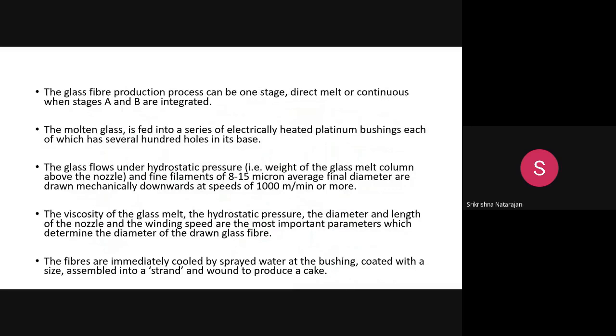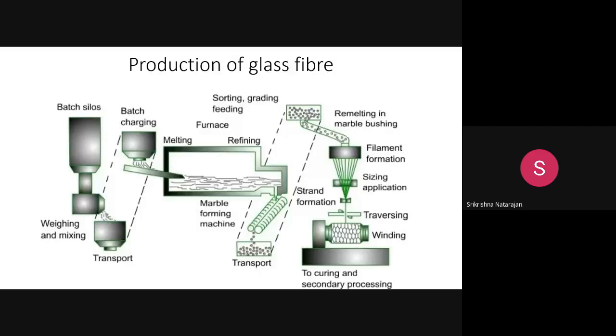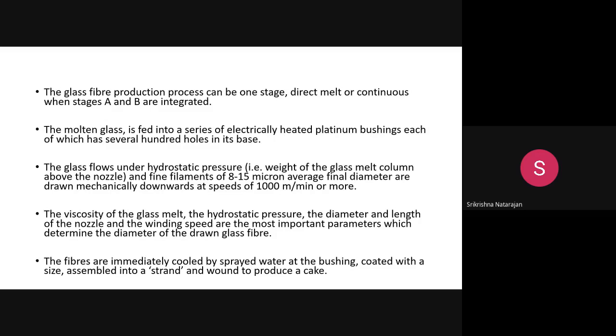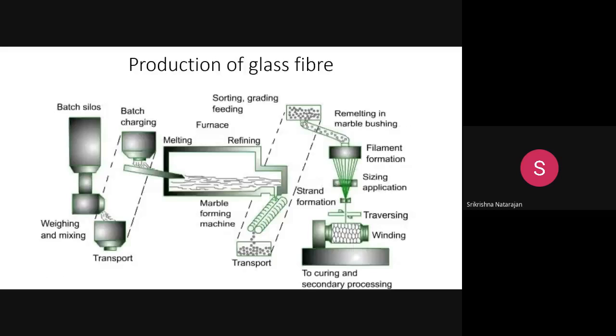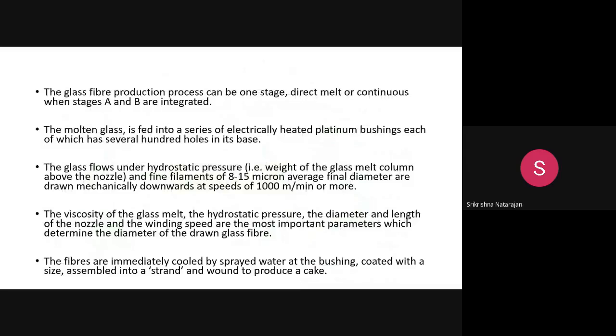So if you want to process it only batch-wise, you can do it, or if you want to do it in a continuous method, that is also possible. The diagram shown here is actually a continuous type of method where the molten glass is fed into a series of electrically heated bushings, which have several hundred holes in the base. You can see here, there are several hundred holes. The glass will flow under the hydrostatic pressure, and fine filaments of around 8 to 15 micron are drawn mechanically downwards at a high speed, say 1000 meters per minute.